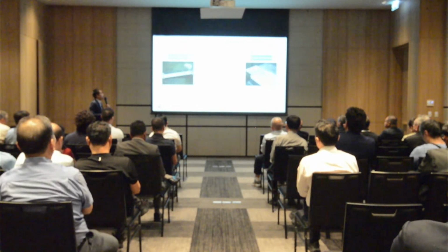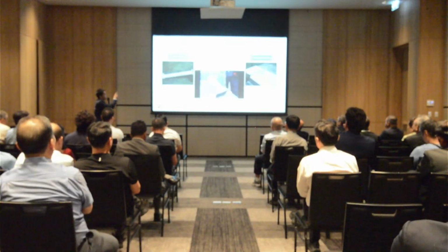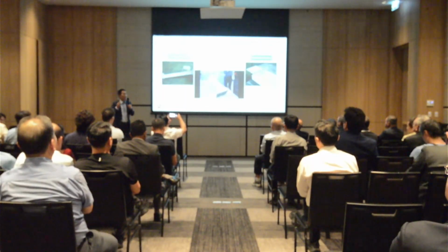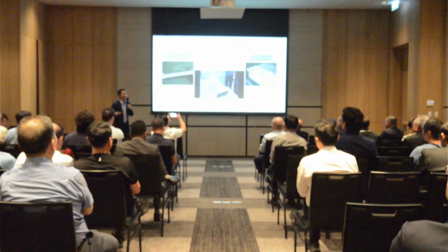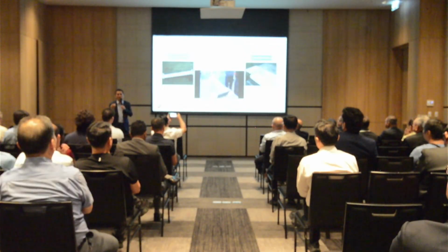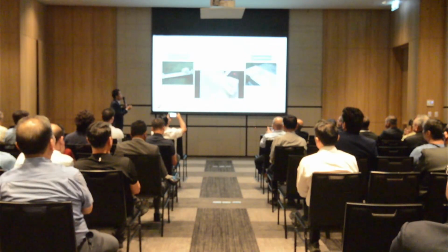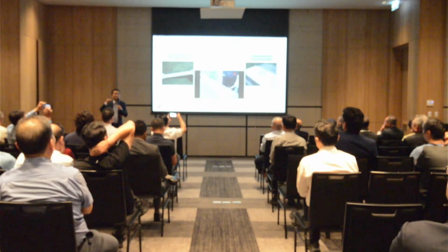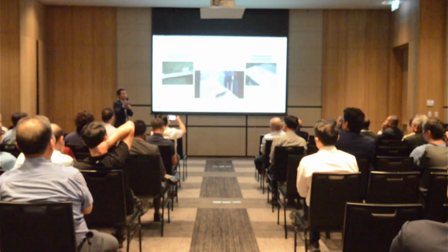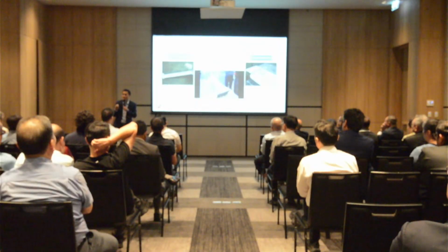But what is GISS? We are here, higher than liquidus. Maybe you cannot imagine it being higher than liquidus, as it should be fully liquid. Why can you get it? That's a non-equilibrium process. How do we make it? It's like we always talk about: hot water with ice. The temperature is higher than liquidus. Hot water, you put ice inside, you still have solid. We call it still solid and liquid, but the temperature is higher.